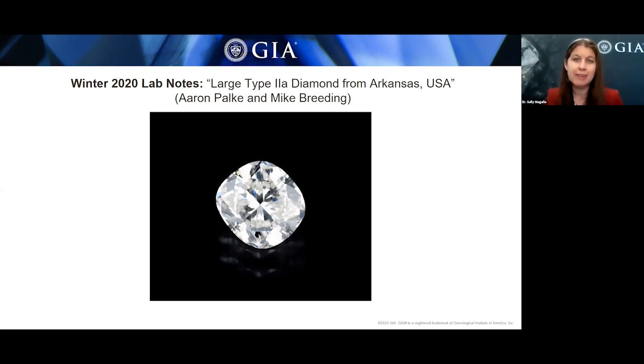At 2.73 carats, the rough was definitely quite large for an Arkansas diamond, as most diamonds found in that state park come in well under 1 carat. The diamond turned out to be fairly clean and with no crystals. However, there was a feather along the crown that gave it an SI1 clarity. But because it had no crystal inclusions, they were not able to perform any additional analysis that might have revealed more about its geological history for that stone or for the diamond deposit in Arkansas.